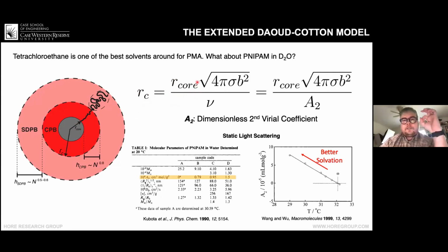If you can get monodisperse smaller particles, then you can keep the same molecular weight of your brush, but you can shift the position of the transition between the two regions. Because these things are all related, at the end of the day what you want is the transition between those two brush regions, and what this value of A2 has to be for that to be true. So by shifting the position like that, absolutely you can further tease out those parameters. Okay, thank you.